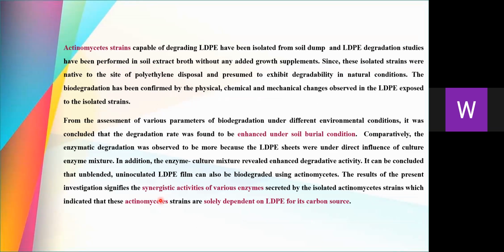Since these isolated strains are native to the site of polythene disposal and presumed to exhibit degradability in natural conditions, the biodegradation has been confirmed by physical, chemical, and mechanical changes observed in the LDPE exposed to the isolated strains. From the assessment of various parameters, it was concluded that the degradation rate was enhanced under soil burial condition. Comparatively, enzymatic degradation was observed to be more because LDPE sheets were under direct influence of the culture enzyme mixture. In addition, the enzyme culture mixture revealed enhanced degradative ability.